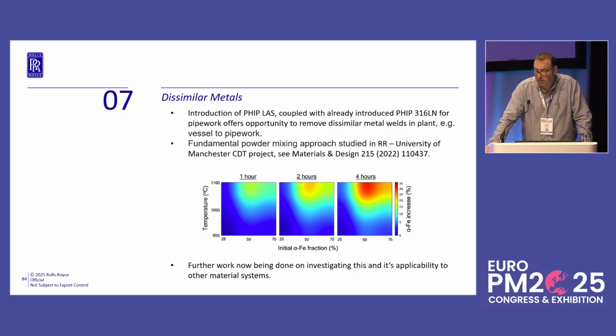What we did is we did some fairly fundamental work trying to understand the metallurgy of the system. And we did that work with the University of Manchester, and this is just an example showing how the microstructure changes as you have an alloy that's pretty much iron and not a lot else, and then you put it next to 316, which has an awful lot of something else in it, and what actually goes on. And we found some really interesting results, which hopefully Manchester will get around to publishing in the near future. But we're now seeing how that can be applied to some of the other systems that we've got, because like everyone else, we have quite a lot of dissimilar metal welds in the plant.